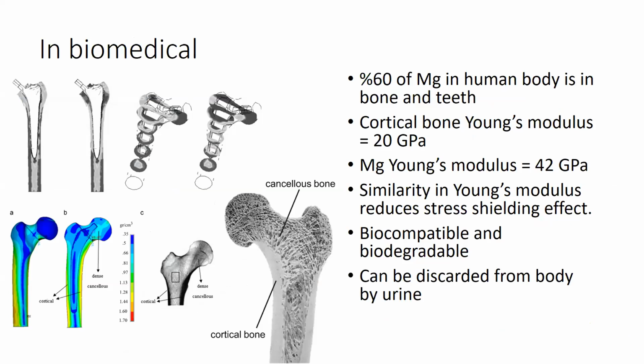Most of the metals used for biomedical applications, such as stainless steel, titanium, and cobalt, have different mechanical properties than human bone. This difference causes the stress shielding effect, which is the change of bone density because of the different stress levels on the bone and prosthesis. However, magnesium and magnesium-based alloys have more similar mechanical properties. Also, the biodegradability and biocompatibility of magnesium make later surgical interventions unnecessary.